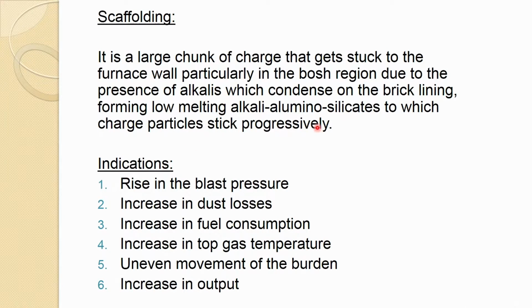So, an indication of this, because it is increasing progressively, is a natural rise in the blast pressure, increase in dust losses, increase in fuel consumption, increase in top gas temperature, uneven movement of the burden, and increase in output. So, essentially the scaffolding is also reducing the area of the furnace. If these things are happening, this gives an indication that scaffolding is happening somewhere in the blast furnace, and one has to look at all these things and take corrective action.